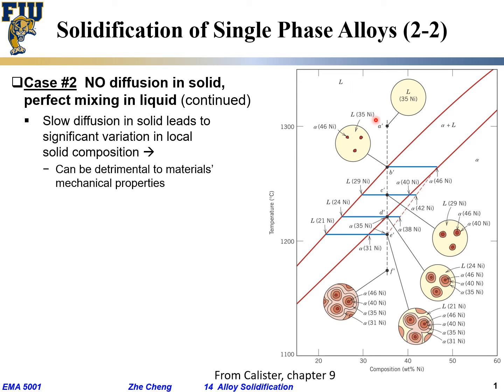Why do people cool slightly faster than equilibrium? It's to accelerate production — time is money. For manufacturing, you don't want to wait forever for equilibrium because it's expensive. So you give up something: you gain efficiency but sacrifice composition uniformity, and as a result, property uniformity. Quite often people have to do some other trick afterward to make things more uniform again.